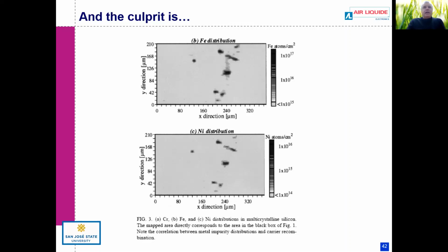So they tend to come together, and they tend to be segregated in this way. So it's information, but it's not necessarily a solution. But it's interesting too, because it's not homogeneously distributed, right? I mean, there's probably hyperpure silicon here, but if on a 300 micron scale it's contaminated, it's probably not of any use.